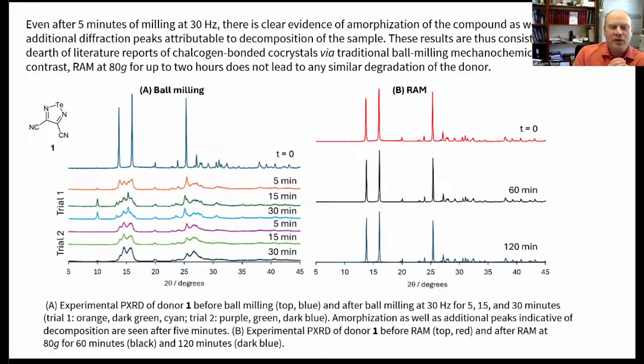Okay, so this is the problem that we had encountered. Again, this donor molecule here, from past efforts from our group, we were trying to make cocrystals of this, but we just kept getting either impure products or amorphous products, not things that we could really use. And if you look at ball milling just the pure donor molecule by itself, at time 0 you see a nice sharp powder X-ray diffractogram. But after just 5 minutes with standard conditions, so 5mm balls, 20-30 hertz, there's a lot going on here. We have some degradation, amorphization, or both, and this happens pretty quickly.